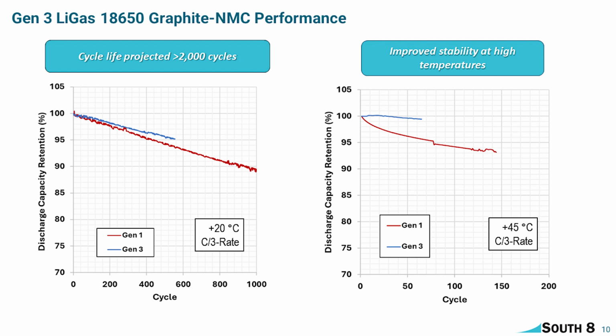Last year I was on this stage, and somebody asked a good question: how is your high temperature stability? I replied, we are working on it. I'm happy to say today that our Gen 3 chemistry is performing much better than our Gen 1 chemistry, which showed some fade at 45 degrees Celsius. Our Gen 3 chemistry is showing significantly better stability here. It's pretty early cycling, but we're pretty confident this will continue cycling over hundreds of cycles. I do want to add that our electrolyte is behaving really well at low temperatures, no doubt.